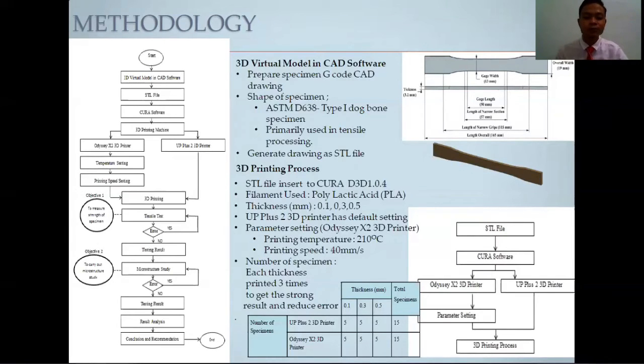So to reduce error during the process and to get a strong result, each layer thickness will be printed into 5 units for each printer. As you can see in the table on my slide, 5 units of part will be produced with 0.1 layer thickness, 5 for 0.3 millimeter layer thickness, and 5 units for 0.5 millimeter layer thickness. So there are a total of 15 units of part or specimen produced by each machine. So there are 30 parts produced for both machines.